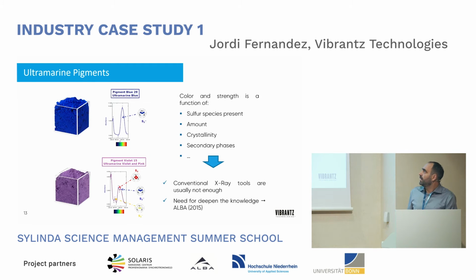Ultramarine blue has, as I told you before, the sulfur species in the ultramarine blue as the most important part to control or tune the color of the pigment. So ultramarine blue has a species that is S3-, an anion radical species that gives this intense, deep blue coloration.